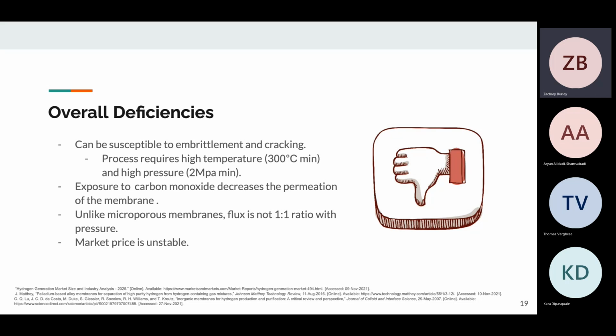Due to the previously stated issue of permeation when used in this application, palladium membranes require a relatively large surface area and must be ultra thin, approximately 1 to 10 micrometers, to be effective and maximize the overall flux. In addition, the minimum operating pressure recommended for the separation of hydrogen is around 2 megapascals. This level of pressure is also required to maintain the necessary flow and flux through the membrane.